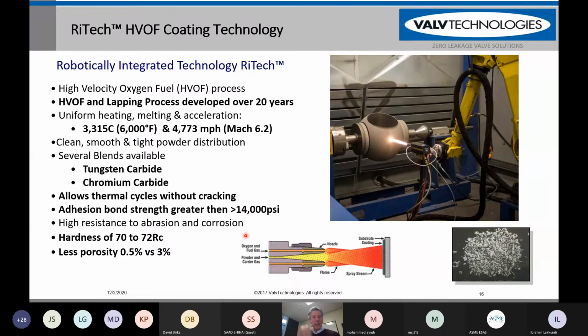That's tested by taking a mandrel and gluing it to the tungsten carbide, and we do a pull test on it to see if we can get the tungsten carbide to delaminate from the ball. The highest strength glue that there is and the highest pull that you can give it is about 14,000 psi. So we do routine checking of the bondage and the adhesion strength of our valves for the tungsten carbide. This is very important because what you don't want to have happen is in the field to have the tungsten carbide start to delaminate. Tungsten carbide and chrome carbide is exceptionally hard and exceptionally durable. It is upwards of 70 to 72 on the Rockwell C scale.